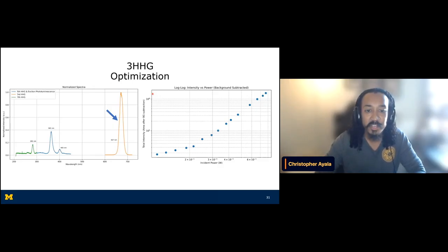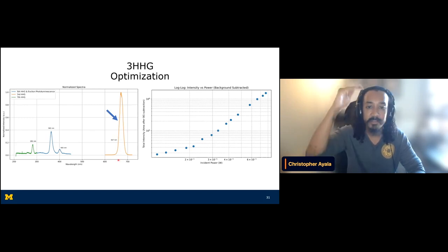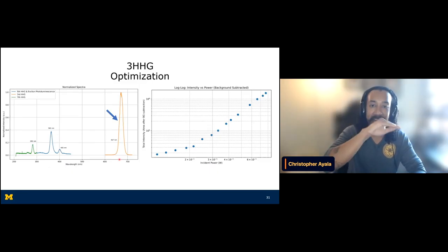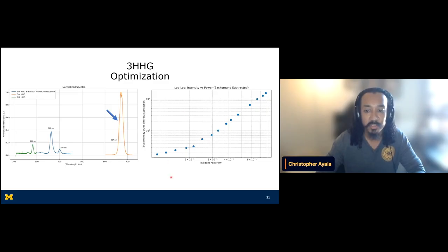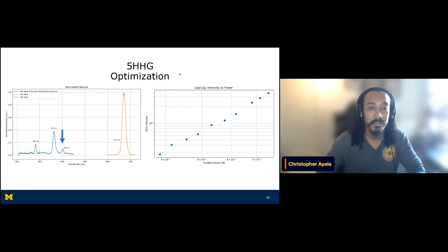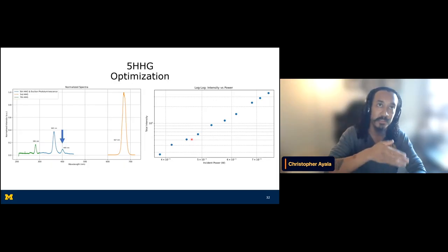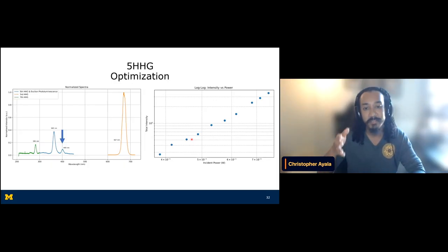I don't have a good representation of a power chart, but if you take the area under the peak and do it for multiple different power levels, you should see that as the power increases, it should scale to the power to the third, I to the third. You would see this occur in both the third and fifth harmonics, that they follow a trend of I to the 3 and I to the 5 for each harmonic order. So each harmonic order should follow its power trend. Third harmonic should follow I to the third, fifth harmonic should follow I to the fifth, and so forth.